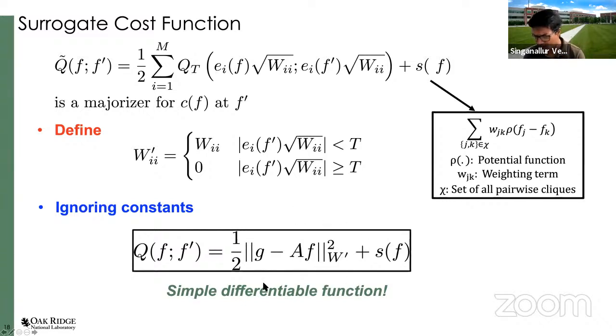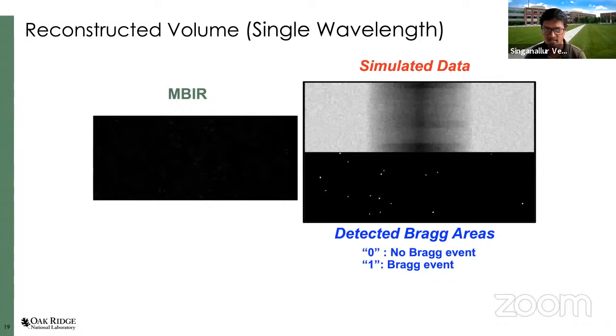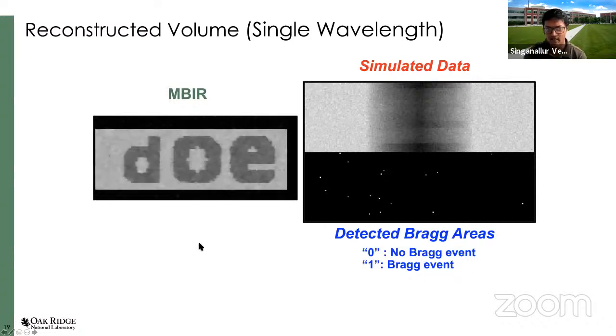And once we have this, there are a whole host of tools. We have just used some first order methods to do the inner minimization, based on the optimized gradient method. So the nice thing is we can now start handling crystalline materials. Here is an example of a reconstruction of the sample we saw earlier. And you can see that in the MBIR reconstruction, we are able to clearly see the letters DOE, which is what the sample was composed of.